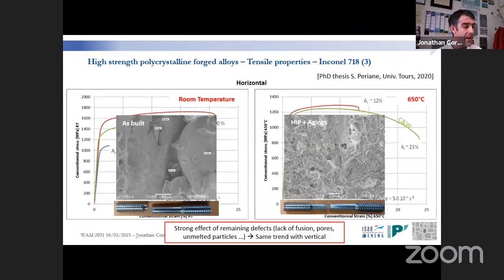From a failure point of view, we can see, linked to this lack of ductility, that crack initiation is mainly coming from lack of fusion and pores remaining in the as-built material, while in the HIPed state, we don't have any more, or very few of them at the end.